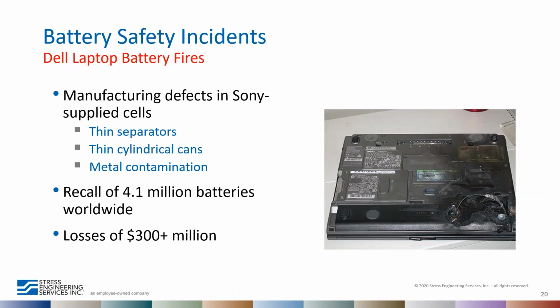So first, starting with the Dell laptop battery fires, the point of origin for these fires was actually manufacturing defects in the Sony cells. The separators were too thin, they're out of spec, along with the cylindrical cans. And as with any manufacturing process, there's always a little bit of variance and in some cases metal contamination. And that can lead to a significant recall, as it did in this case, and significant monetary losses as well.